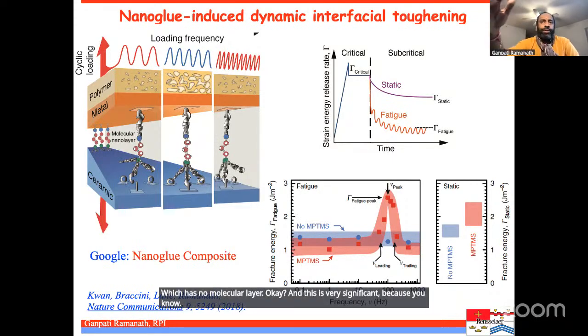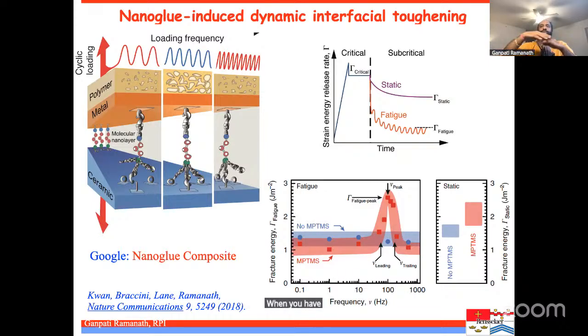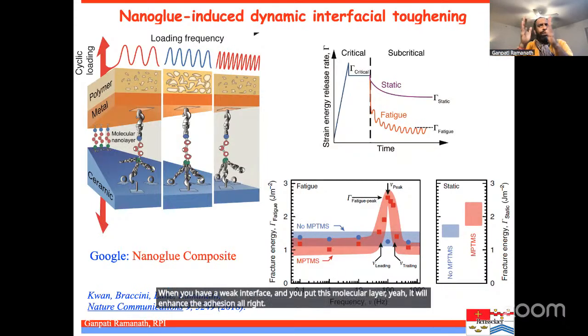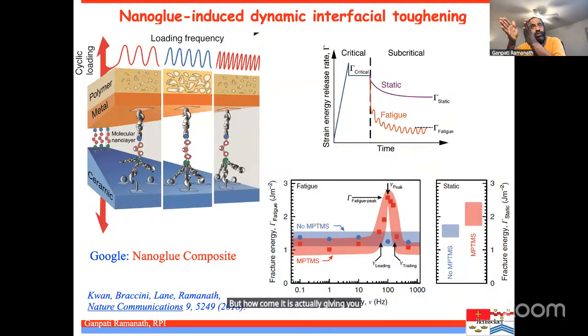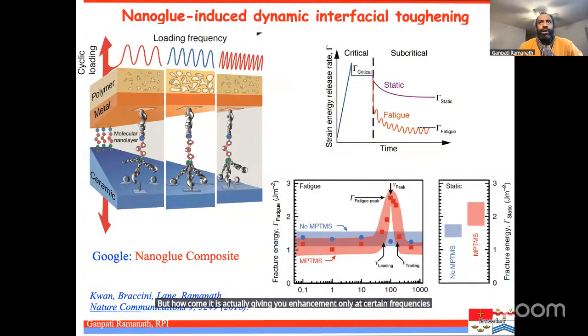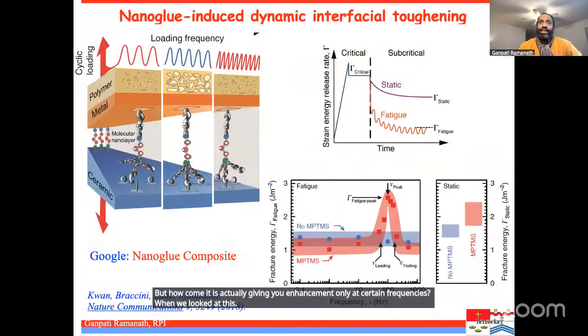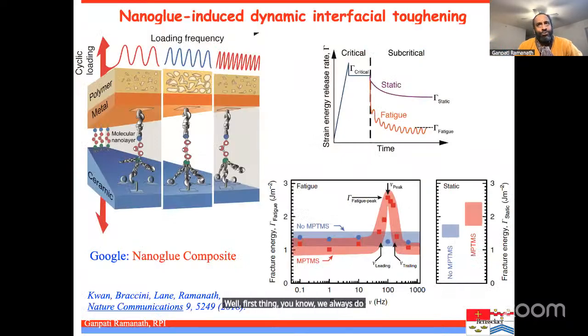normally when you have a weak interface and you put this molecular layer, you will enhance the adhesion, all right. But how come it is actually giving you enhancement only at certain frequencies? When we looked at this, well, first thing we always do when we find a new thing is try to make the effect go away.